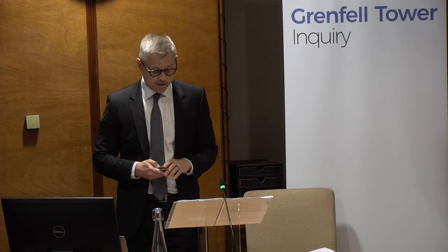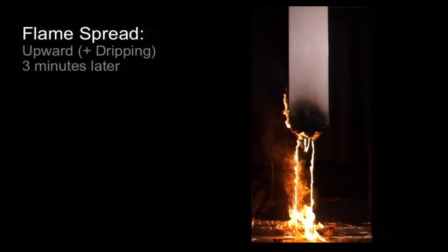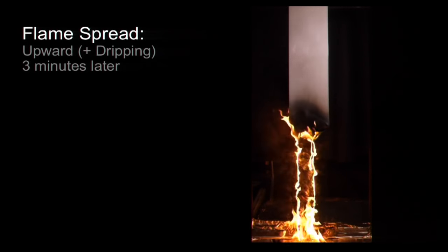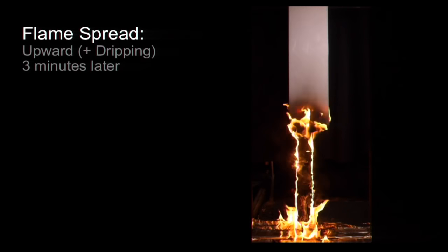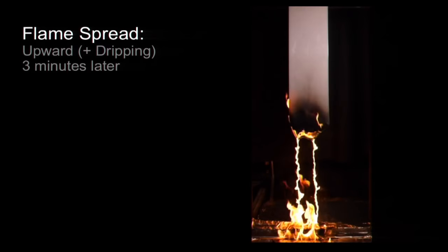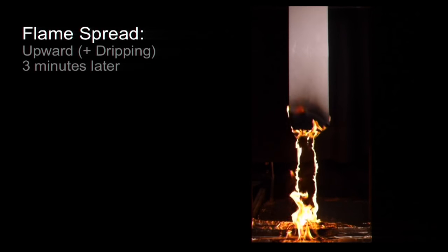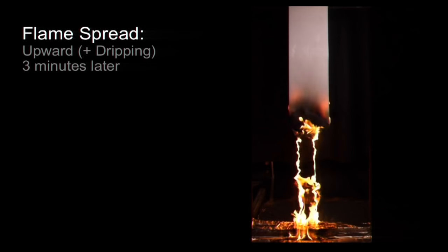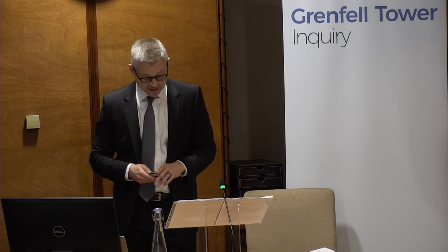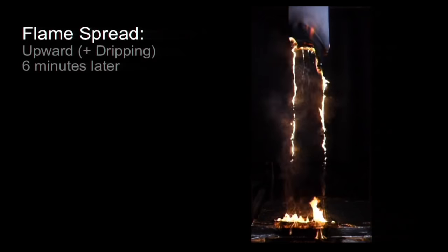In the second segment, which begins about 3 minutes later, we see that the sample is burning on both sides and that there is an almost constant flow of molten, burning polyethylene falling from the sample to the floor. And I should point out that the vertical streaks are rivulets of melted, burning polyethylene. In the third segment, which begins about 6 minutes later still, the sample has been significantly consumed and molten polyethylene continues to fall.